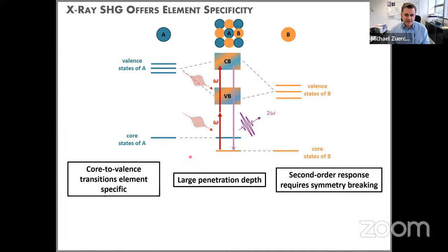If we can do this, we have several advantages that come from that. One is that we are element specific. By selecting this transition energy properly, we can select the response of one and only one element in a very complex setting, say with a complex liquid, complex molecules around, or a condensed phase system at an interface, and can still study the response and charge transfer as perceived from one specific element in the system.